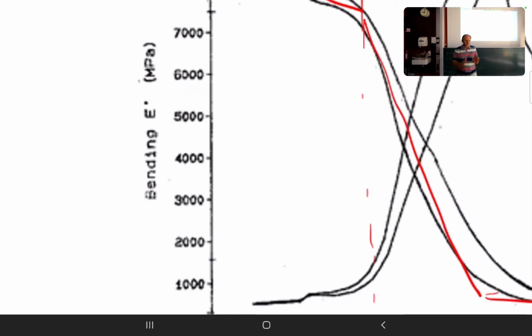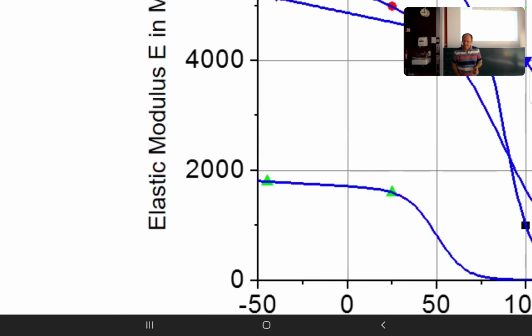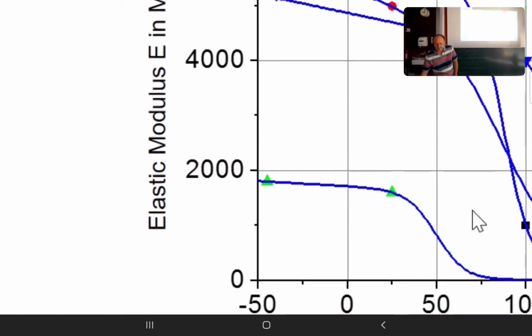Also, we must say, for die attachment materials, the CTE itself is not so relevant. Typically, the Young's modulus is more relevant because it decouples or it removes stress from the chip. Again, here we have seen for the different materials how it behaves over temperature, and here we can see there are materials also which have glass transition temperature, for instance, roughly 120 degrees centigrade, and others have a glass transition temperature only around 50 degrees centigrade.